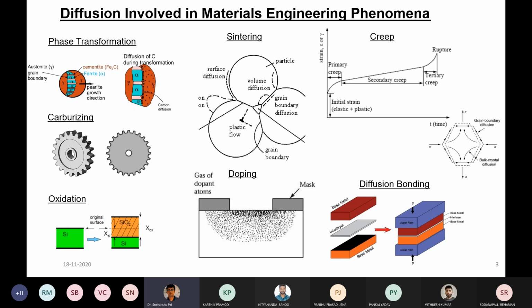At low temperature, generally dislocation mediated deformation processes are dominant. But at high temperature, diffusion is also an important thing, and diffusion can take care of a lot of things. How diffusion will be contributory and how strongly it can govern the creep process depends on the temperature of the creep process, as well as the microstructure of that particular metallic system or alloy with respect to grain size.